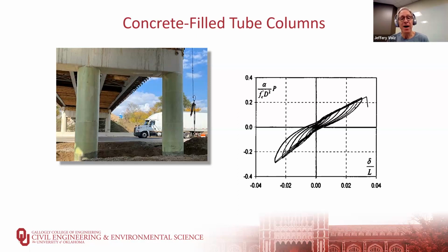You still get some nonlinear performance, so you do get a hysteresis loop that has some energy absorbing ability, but because of the behavior of the FRP, there's not as much area, there's not as much energy absorption and not as much ductility, and the column example on the right failed at about a ductility ratio or drift ratio of 3%. But still an important performance improvement with regard to durability, but like all things, they have advantages and disadvantages, and so you don't have as much energy absorption capability, and therefore the ability to resist these hazards.